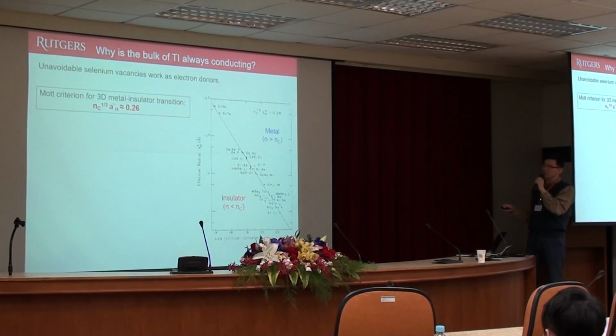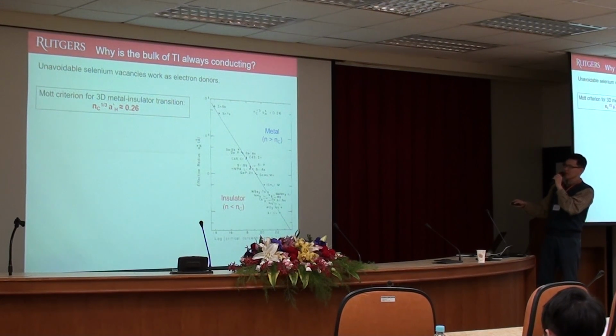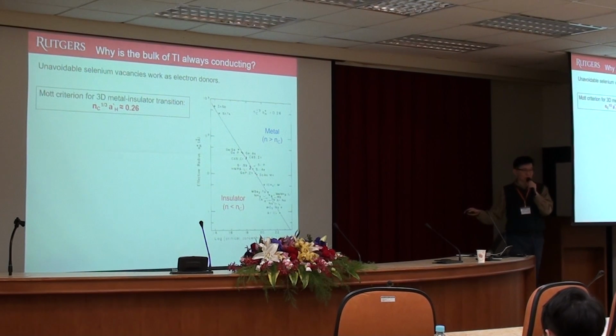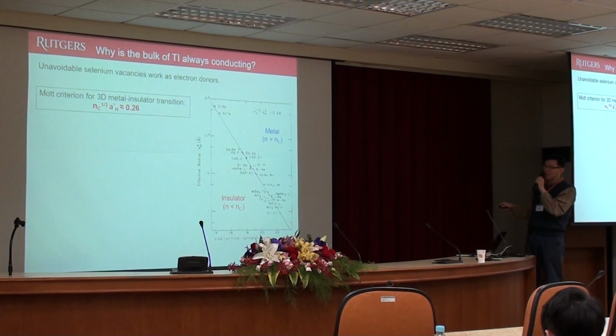if your defect density or doping density is larger than some critical value, then they behave as metal. That means if you cool it down to zero temperature, they remain metallic. But if the doping density is below the critical value, which is determined by the so-called effective hydrogen Bohr radius of that particular material.